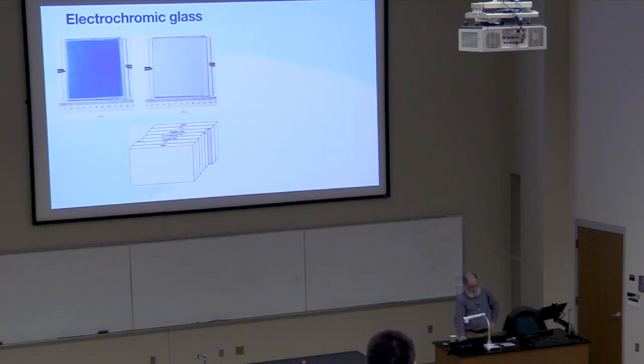I'm not sure if it helps or not, but you can see here's a front piece of glass with a coating, and there's a little silver contact there. Here's the back piece of glass. You can see they're offset. So that's what we're doing here. This alligator clip is connected to this glass. This alligator clip is connected to this glass. And then there are those magical coatings in there that when you apply a voltage, the coating turns blue.